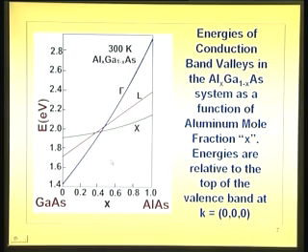Why I put this diagram to you is to get further clarity about this particular diagram. Also, when you take x about 0.4, you get about 1.93 or so, somewhere here. From this diagram, if you just draw straight lines, you will not get that 1.93. In fact, earlier when I drew a straight line, I put 0.3 corresponding to that, but it is a very crude approximation. The real thing is that.